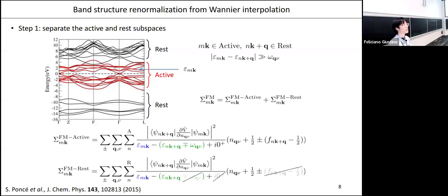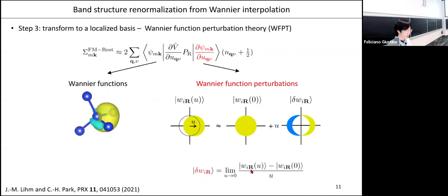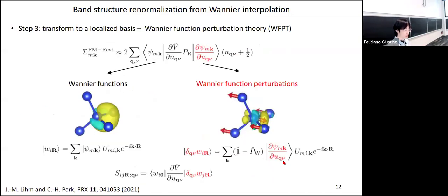What are the ingredients for this technique? Like, you need to do DFPT first. Where do you get the response to the potential perturbation? Yeah, so thanks for the question. So the ingredients are almost the same as a usual EPW calculation. You have to do the DFPT. You need the Wannier functions. The only additional ingredient is that you need this wave function perturbation. So in the tutorial, we will have an additional step in the workflow that calculates this wave function perturbation and these matrix elements on the coarse k-point mesh. And then using EPW, we will transform them to real space and then perform Wannier interpolation. So this is the only additional ingredient to the usual EPW workflow.